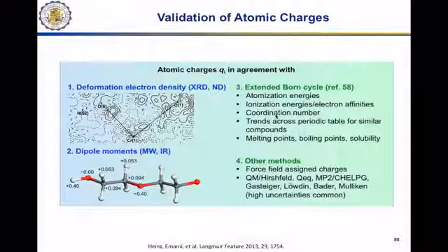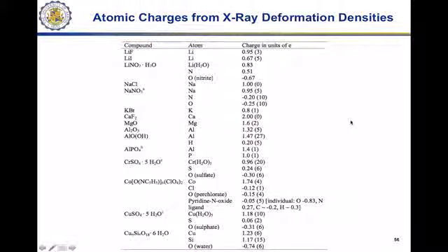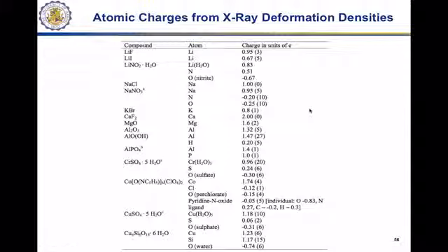And this is what we use, and there also we see that the accuracy of such atomic charge assignments is actually better than plus or minus 0.1 elementary charges, or less than 10% error for small atomic charges. And that is a huge improvement over using ab initio methods, because the spread in those methods can sometimes be factors of multiples, a huge uncertainty, and then when this is not properly implemented in the force field, we end up with huge errors, up to such effects that we don't even have a stable structure in the simulation.